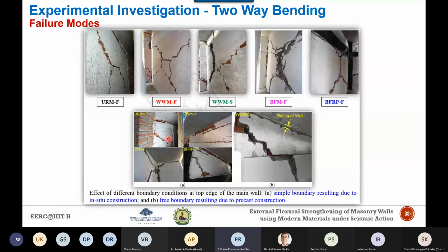Here you can see that all the test walls with the suffix F represent my rigid diaphragm, and this is the only wall which represents my free boundary resulting due to the precast construction, that is my flexible diaphragm. Here you can see that in all the tested walls with the rigid diaphragm boundary condition or integral boundary, the last course of the brick basically acted monolithically with the RCC slab during this out of plane loading. As a result, the horizontal cracks have developed one or two courses below the ceiling line.